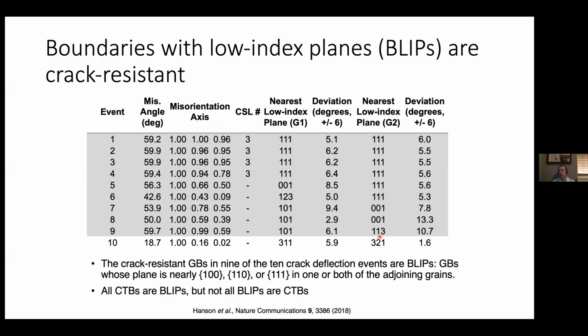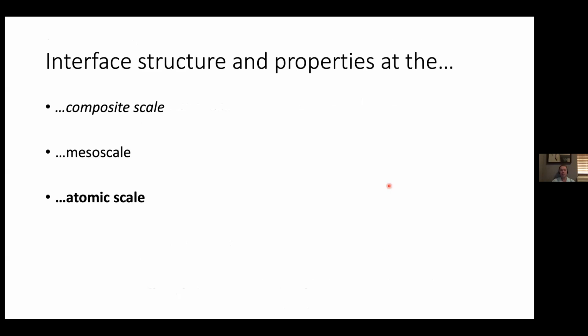Here, this one would not be considered a low index plane. This is just for grain 2. If you look at grain 1, it has a low index plane, 101. And then here is a 123, which we would again not consider low index, but the matching grain is a 111, so that's low index. There was only one strong boundary whose plane was not a low index plane. Okay, so this is a very good correlation between the strength of boundaries and their crystallographic character. So this is an example of how we can study grain boundaries at the mesoscale, at the level of individual grain boundary properties. So that's vignette number 2.